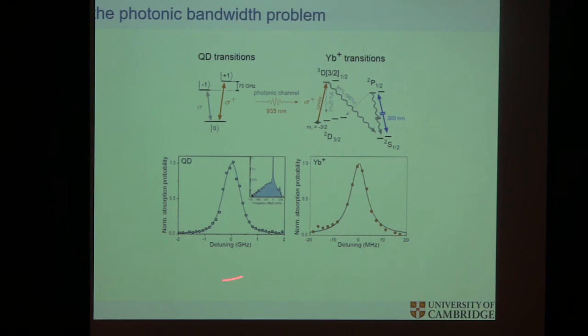This is amazingly narrow for quantum dots, fantastic, and this is incredibly broadened due to cavity, which is otherwise in the kilohertz range. But despite that, this is a big mismatch between the two, and we're able to get quite reasonable coupling, almost as strong as a laser in this system.